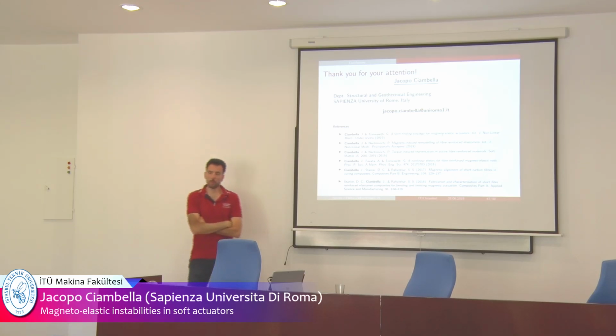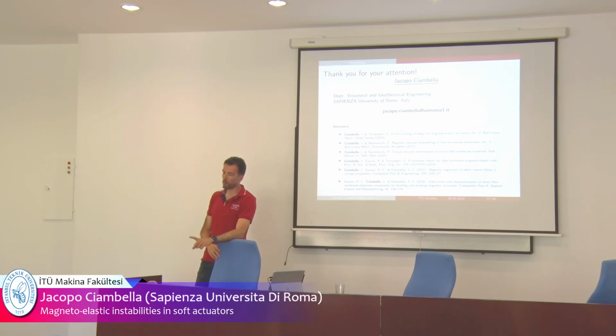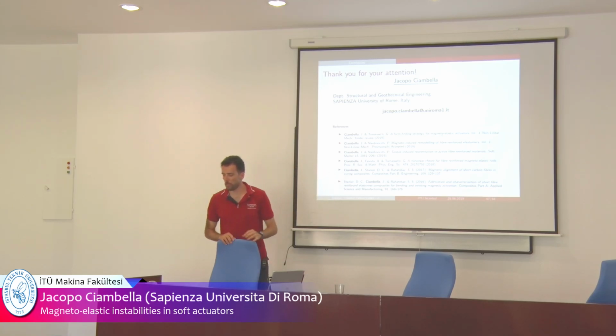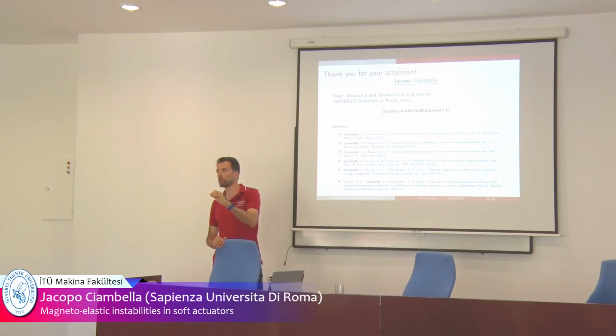If you have the proper equipment, this specimen was very small, so it's a matter of scale. The specimen was 20 millimeters, so about 2 centimeters. But if you have the right equipment, you can, in principle, control the magnetic field locally, very close to the specimen, with a probe or something like that. And this would help with the local orientation for manufacturing. I'm not sure it would help with actuation, because for actuation you want to stay far away from your specimen. Imagine that you can scale down this process and use it for moving an object in your vein. In your vein, you have an external field which is on a larger scale than the scale of the vein, so the field is almost uniform.